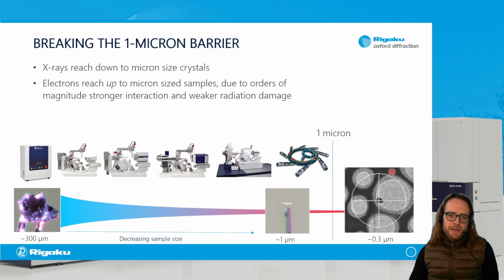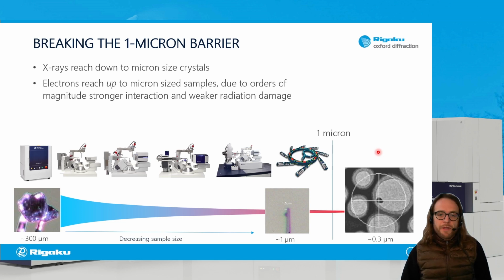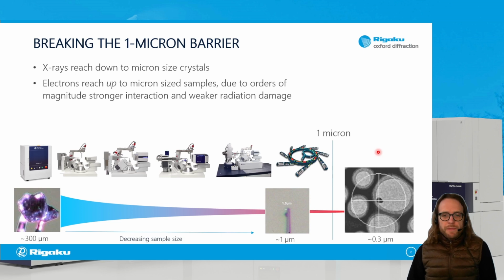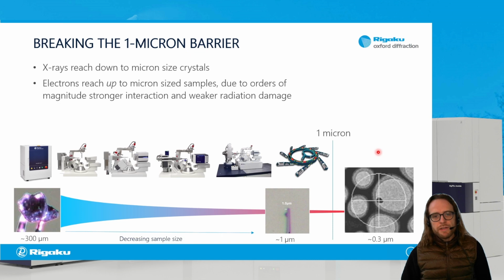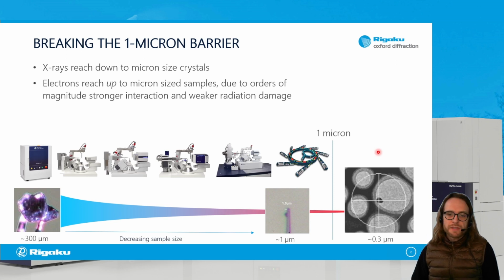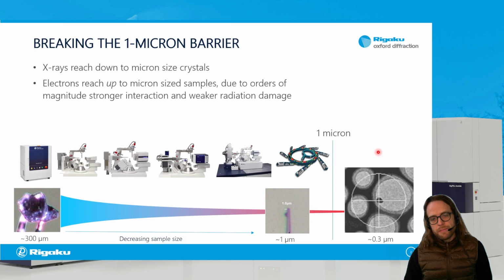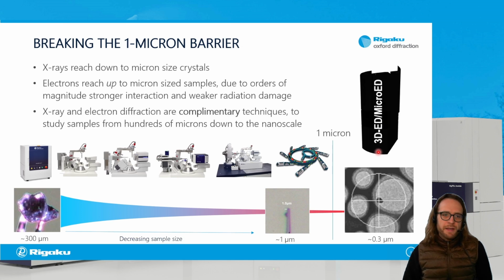So electrons can actually access exactly this regime of up to 1 micron, and only up to 1 micron, because any crystals larger than that essentially act as a beam stop for the electron beam because of the very strong interaction. Also, the specific damage caused by an electron beam to any sort of molecules is weaker than for X-rays, so you can extract full structural information from a single small crystal without entirely destroying it. And I think it is clear from that X-ray and electron diffraction are nicely complementary techniques, such that with this portfolio of instruments, you can study crystal sizes from the mesoscale all the way down to crystals that are only hundreds of nanometers large.